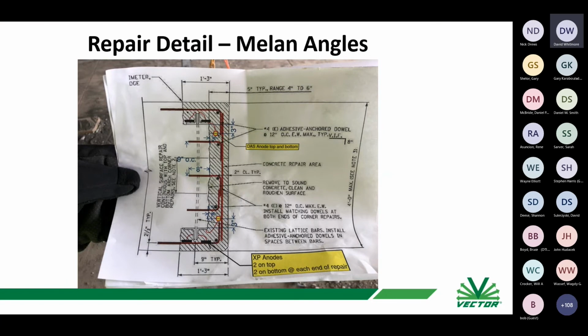So Arnie showed you one of the details for the corner repairs. You can see the similar thing here, and in the repairs, the discrete anodes, for the people that are online, they can't see my pointer. At the top and bottom of the repair, there are 2 discrete anodes that are intended to protect the end of the Melan steel where it protrudes into the adjacent concrete. And then along the length of the Melan steel, what's shown in yellow on this drawing are the distributed anodes that run along the length.